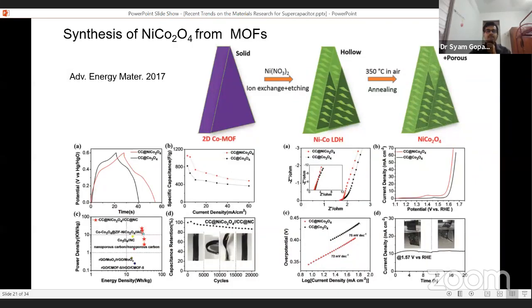An example of improved performance of this nickel oxide is the synthesis of this material from metal organic frameworks. It's a very nice work which has been published in Advanced Energy Materials in 2017, which considered that this ion exchange etching could produce this hollow porous nickel cobaltate material, which will be used